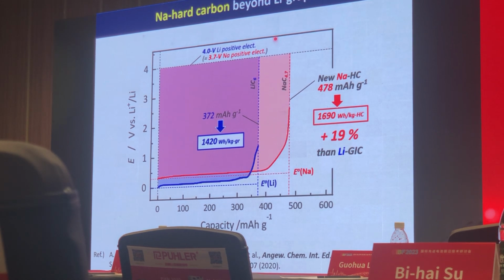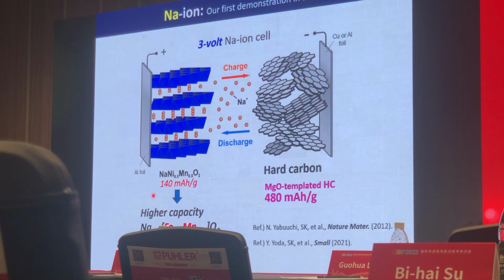This means that the area surrounding the positive and negative potential variation, this red area, is 20% wider than the blue area of the lithium ion cell energy density, which is highly advantageous to demonstrate a high performance sodium ion battery compared to lithium. So not only negative electrodes, but we are also recently focusing on positive electrodes.